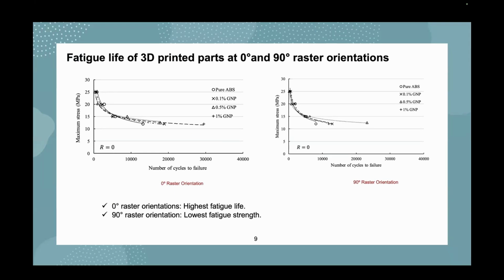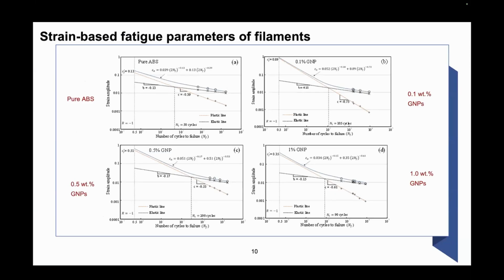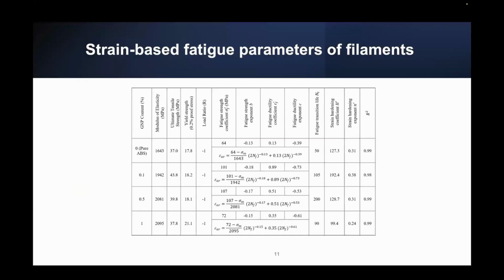So here we can see the fatigue life of 3D printed parts at 0 and 90 degree raster orientation. Samples with 0 degree raster orientations experienced highest fatigue life, while samples with 90 degree raster orientation possessed lowest fatigue life. Also, we can see that adding 0.5% and 1% GNP, especially in high cycle fatigue, experience highest fatigue life for both raster angles. In this slide, we can see that we have used these SN data to obtain strain-based fatigue parameters. And the data has been summarized in this table.